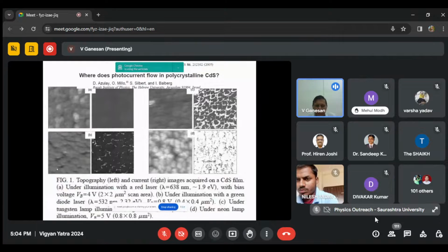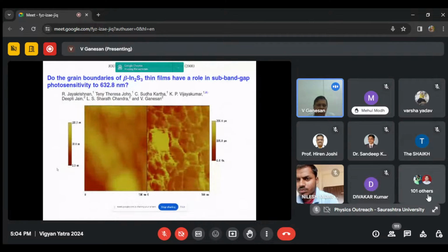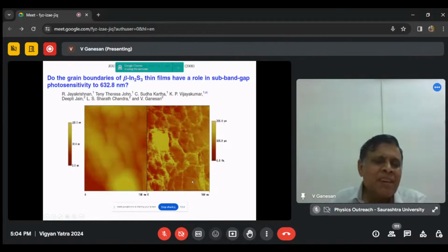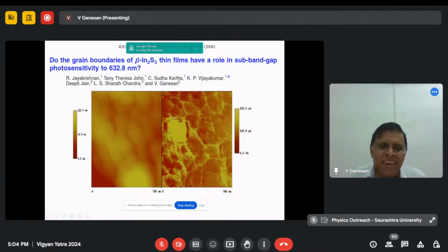Then we had a very beautiful experiment to show how grain boundary conductivity can take place in the system. You see in this there is a sub-band gap excitation. Why does sub-band gap excitation come out? It has nothing to do with an indirect band exciton. It is because the defects produce states in the gap. Therefore, the energy to activate from the band to the localized states is very small. So instead of something like 2.5 eV, conduction starts even at 1.5, 1.2 eV. So we can study this. That's why the grain boundaries have sub-band gap photosensitivity.